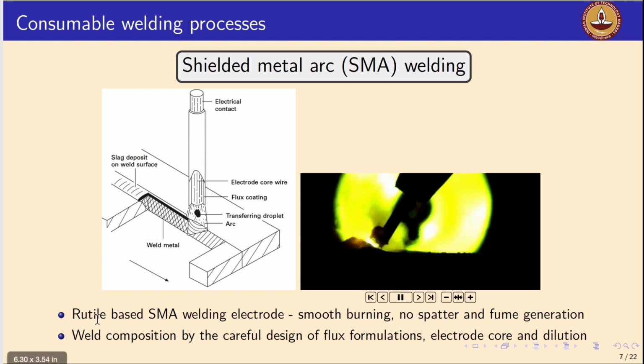So the electrode generally contains a rutile-based flux because of smooth burning and no spatter and fume generation, and rutile-based electrodes are also known to generate hydrogen. And hydrogen induced cold cracking can be a big problem. But this is one of the electrodes which can ensure self-lifting of the slag, so slag intrusion can be avoided. So therefore, we still prefer to use a rutile-based electrode despite the problem with hydrogen induced cold cracking. But we can play around by carefully controlling the weld thermal cycle, which is what I'm going to discuss in the next few slides.